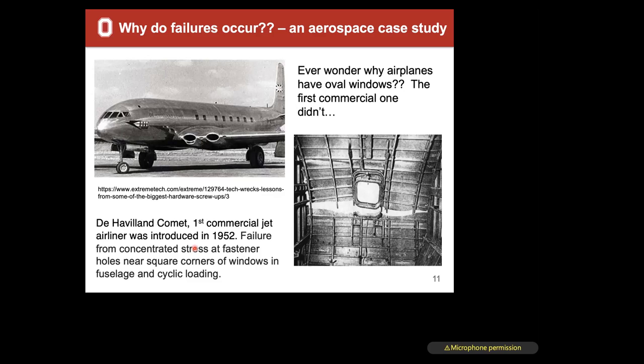Each of these individual planes had made around 1,000 total flights. And all of a sudden, after about 1,000 or so flights, these jetliners were just completely busting apart. It turns out they first made square windows on these planes, and these square windows were failing. You can see here in the fuselage a big crack that has occurred. There are also some rivets put in to hold different parts of the plane together and put the rib structure on it.